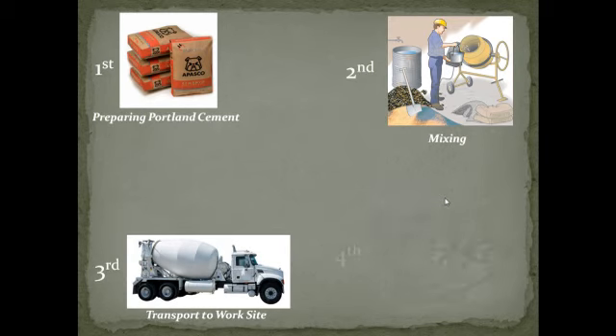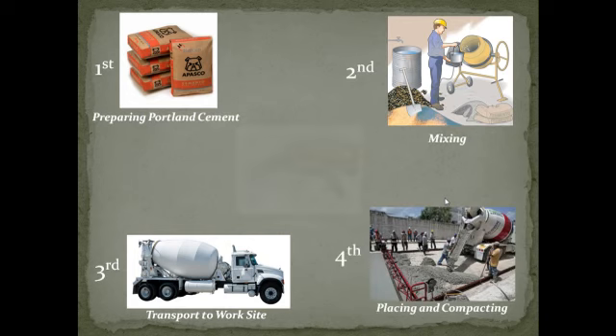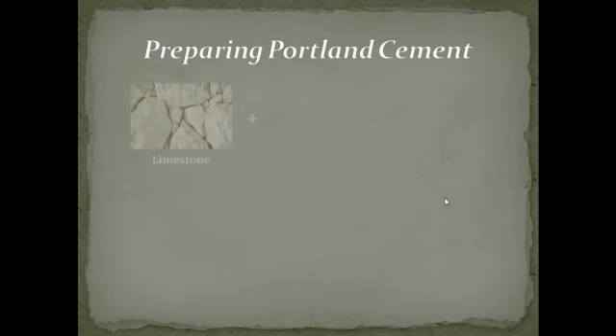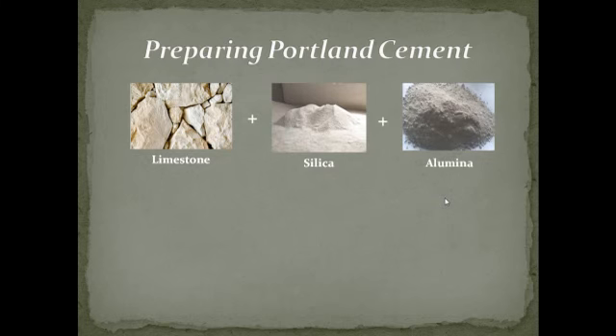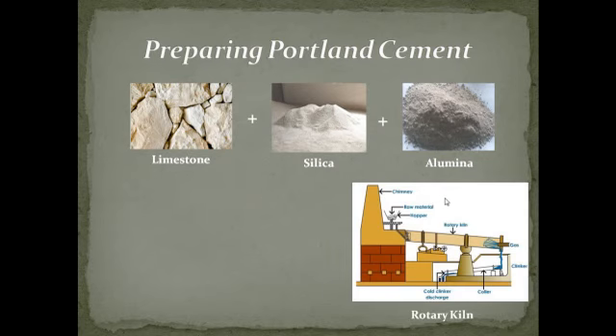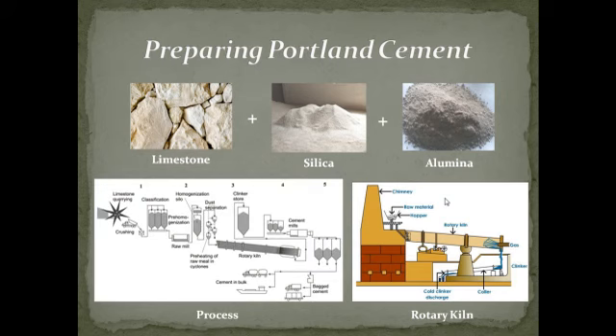Preparing Portland cement. The limestone, silica, and alumina that make up Portland cement are dried and ground into a very fine powder, mixed together in predetermined proportions, preheated, and calcined, heated to a high temperature that will burn up impurities without fusing the ingredients. Next, the material is burned in a large rotary kiln at 2,550 degrees Fahrenheit. At this temperature, the material partially fuses into a substance known as clinker. A modern kiln can produce as much as 6,200 tons of clinker a day.